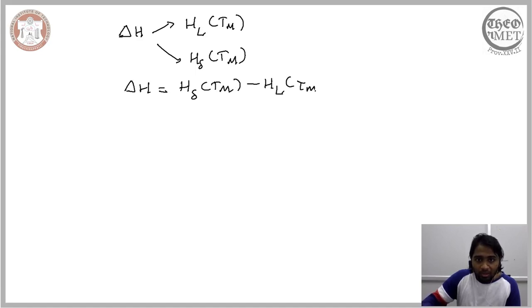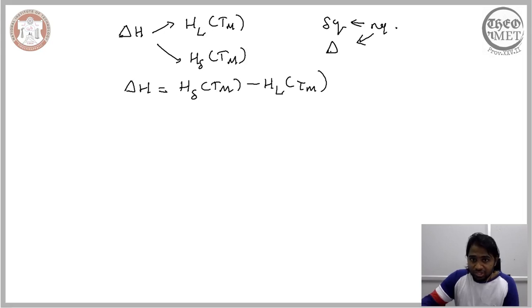Both are at the same temperature, and because the heat is being removed from the system, by convention delta Q is negative, and since delta Q is nothing but the change in the enthalpy, it is also negative. So that means this difference, the enthalpy associated with the solid minus the enthalpy associated with the liquid at the temperature just below the melting point, is less than 0, meaning negative.